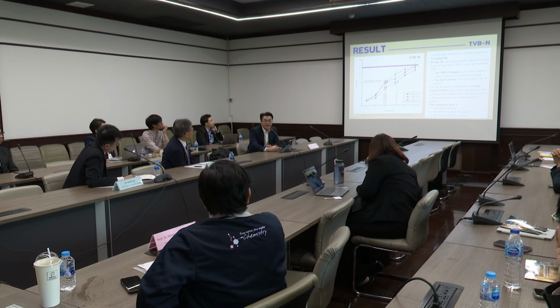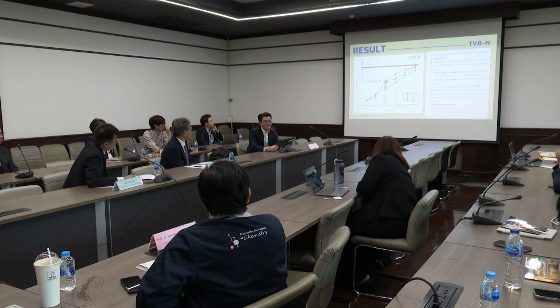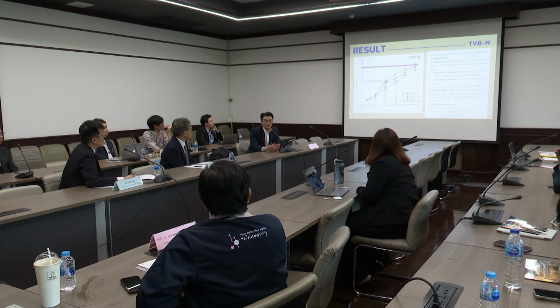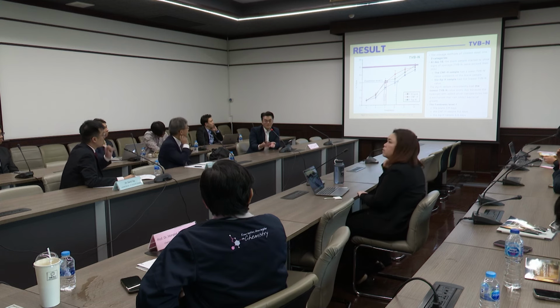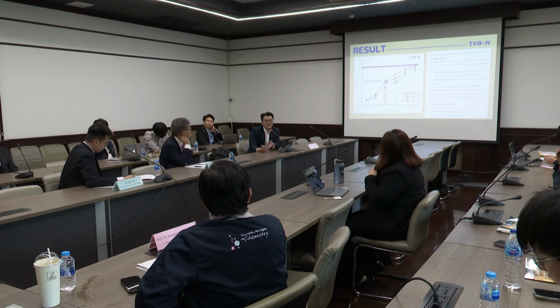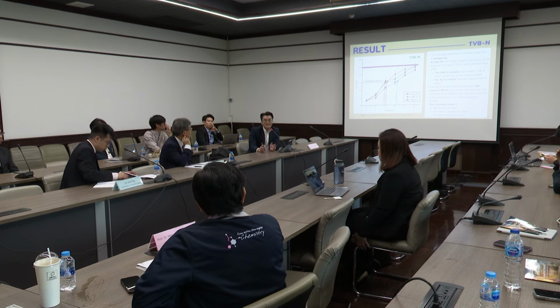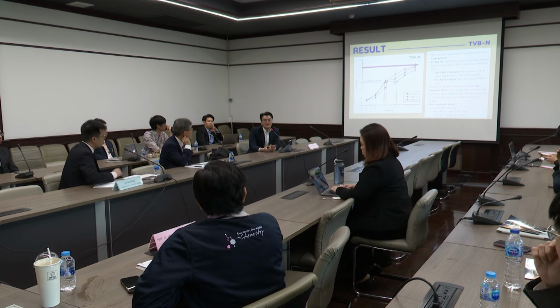From your presentation, when you use less silver, like I think it's 0.008, you also have 100% antimicrobial in the lab. So why do you choose to use 0.015 instead of 0.008, which will cost a lot less and still be effective? Okay, this is a good question, because we already used the 0.008 phr to test the TVBN and the result showed not quite good enough when we used it in practice with real meat. Maybe because real meat has many microorganisms, so it may not work. So we selected 0.015.